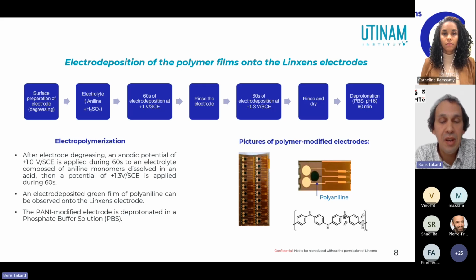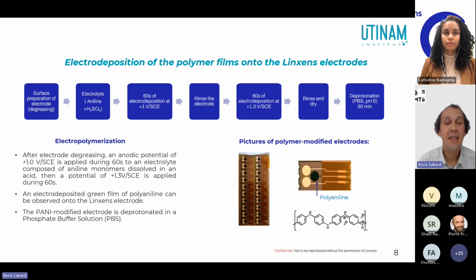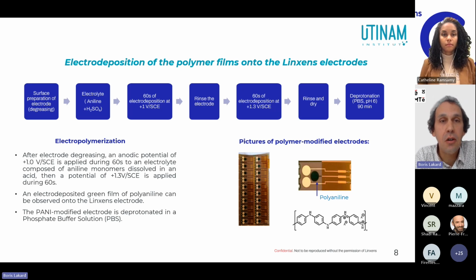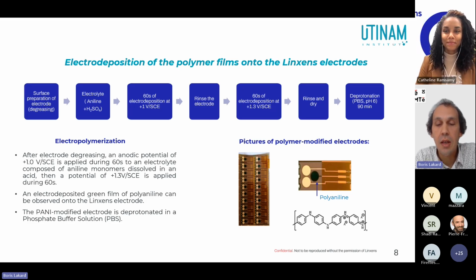We decided to perform the electropolymerization of polyaniline on the Linxens electrodes. We decided to use a polyaniline film as a sensitive material for pH sensing due to the presence of many amino groups that can be protonated or deprotonated. Here you can see the sequence of electropolymerization. After degreasing the electrodes, an anodic potential was applied to an electrolyte composed of aniline monomers dissolved in sulfuric acid. Electropolymerization resulted in the deposition of a green film that can be seen in the photos on this slide. You can see the green deposit on the sensors.